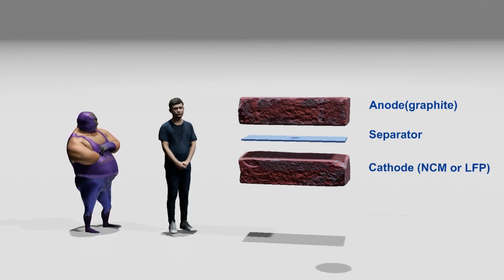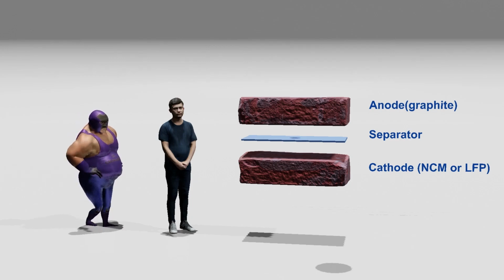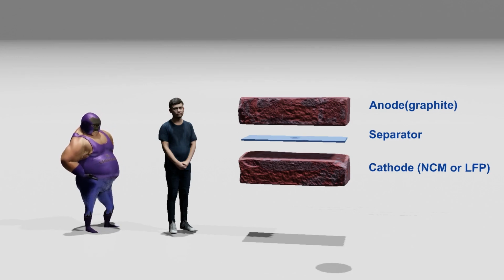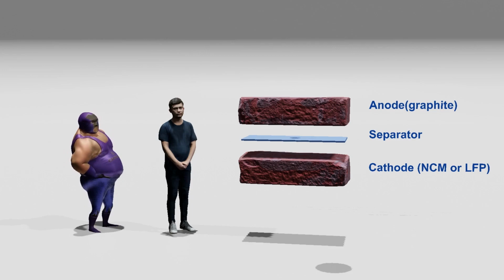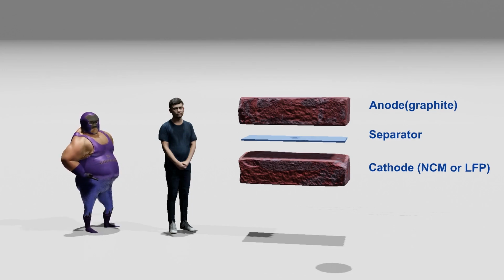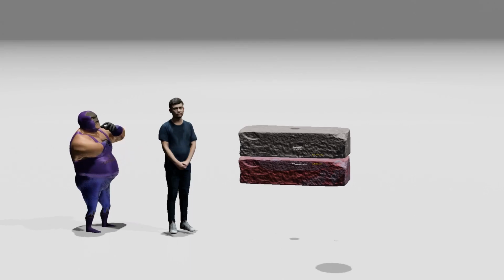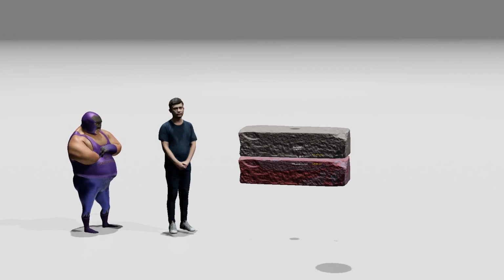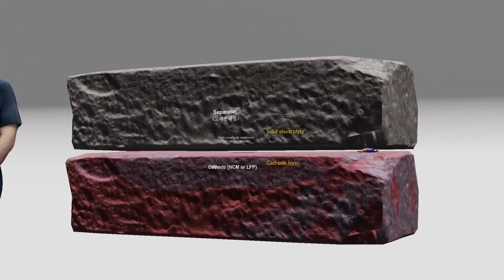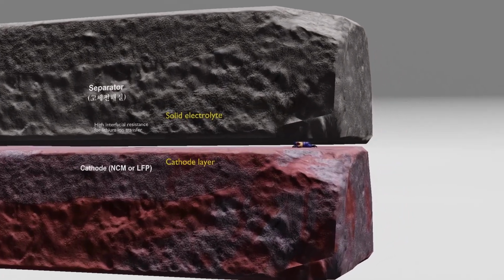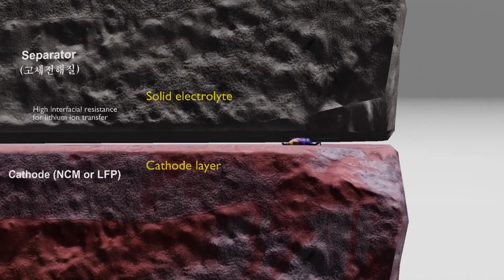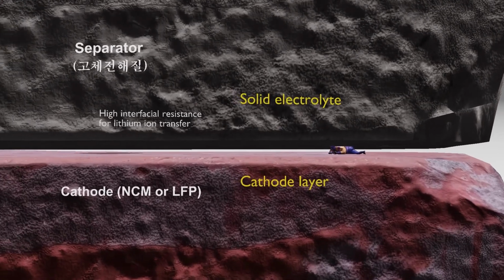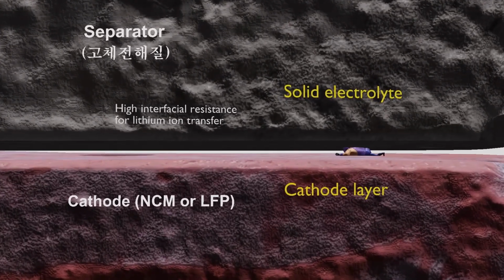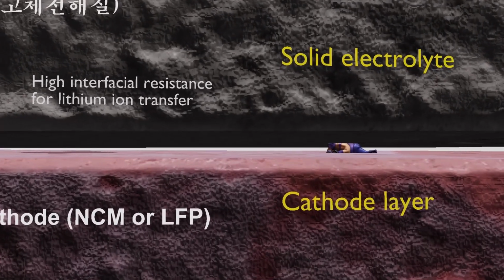However, since conventional batteries use liquid electrolyte, lithium ions could naturally permeate through the gaps while wetting the bricks. In addition, a polymer separator is placed between the bricks to prevent them from contacting each other while allowing lithium ions to pass through. On the other hand, in an all-solid-state battery, an electrolyte composed of a hard solid is placed between the anode and cathode. If these layers are simply assembled, small empty spaces exist between the solid layers, making it very difficult for lithium ions to move from one layer to another. In technical terms, it is expressed as having high interfacial resistance, which is acting as a major obstacle to the commercialization of all solid-state batteries.